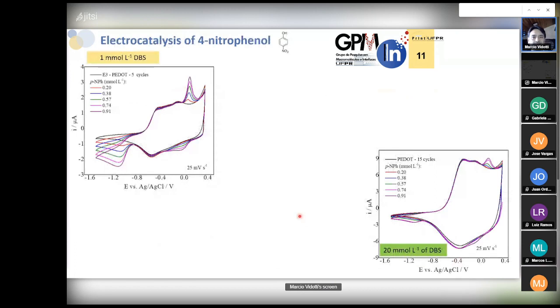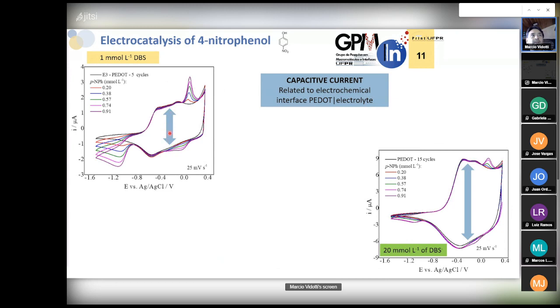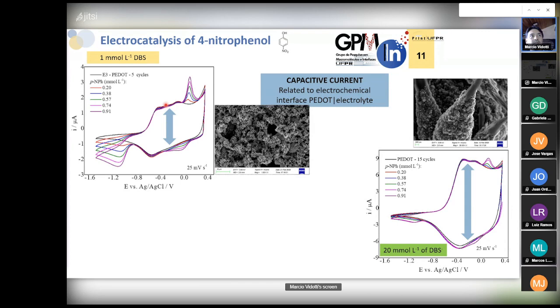And to study the catalytic performance of the electrode, we have done the voltammograms of the material, as I said, and we have shown that the capacitive current of this kind of electrode compared to this one increases higher in the presence of these templates, because somehow these structures allow higher energetic surface interfaces. So the capacitive current, which is related to the double layer structure, somehow is enhanced in the presence of the polymeric structures grown on the templates.